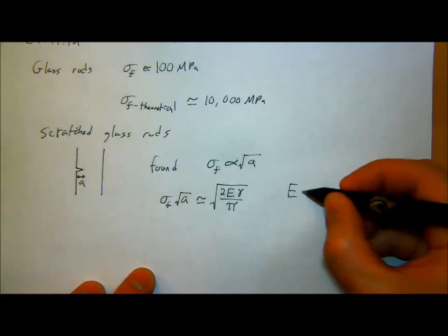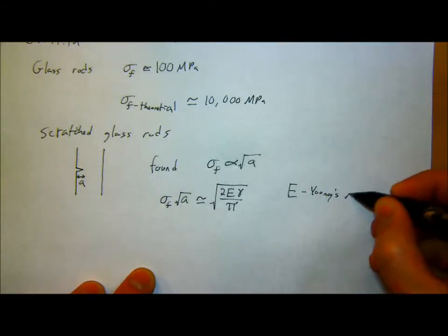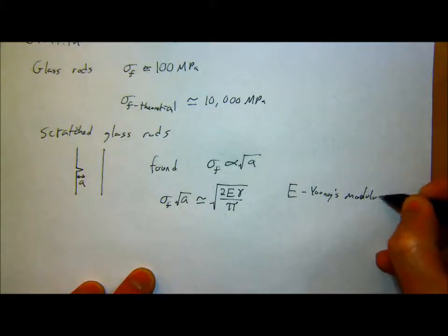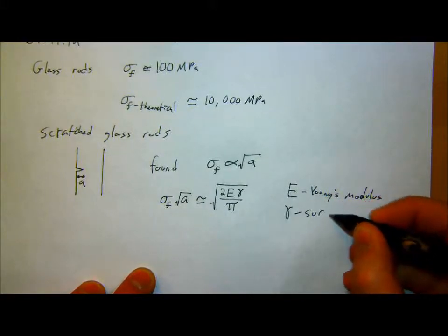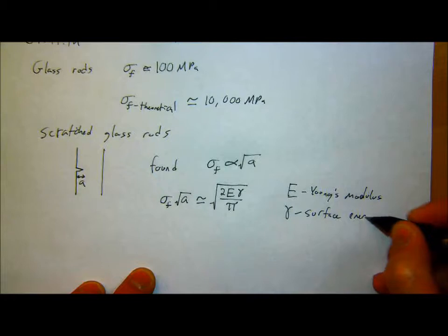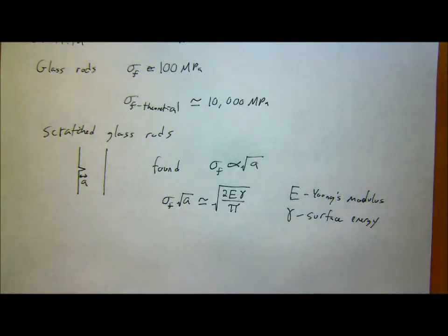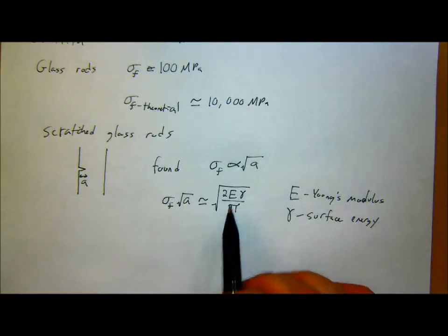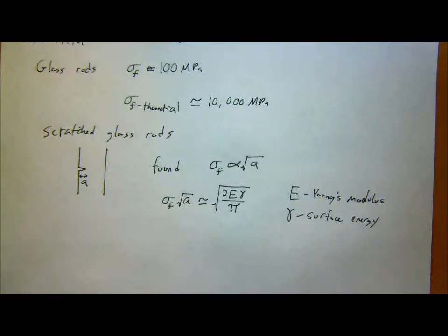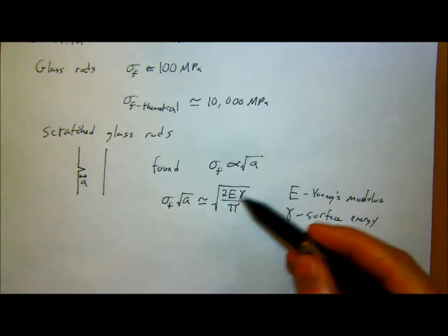So the way he logicked it, basically, was saying in order to cause a crack to form, I'm creating new surfaces. So if I open up a material and I take something that was solid and I make two new surfaces, the amount of energy that I dissipated in that process to create those two new surfaces is that surface energy. So my fracture strength here is then equal to this quantity.